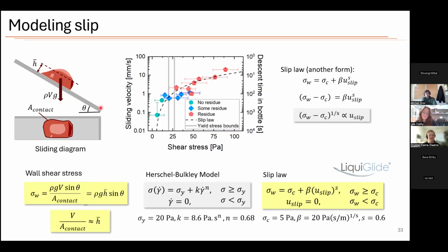So it's just something that has exceeded that stress. And it's only in this very narrow region where you are above the critical slip stress, which is set by the plastic bottle material, and between that and the yield stress, that it's able to slide. It's under little enough stress that it's just above one critical stress but still below the other, so it's able to slide without internal shearing. So I guess this is similar to the adhesion versus cohesion point. It's only interacting with the material, but it's able to slide as if it were a solid. Okay, I see the point. Okay, thank you.